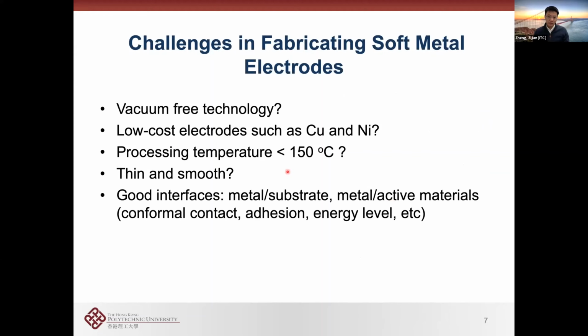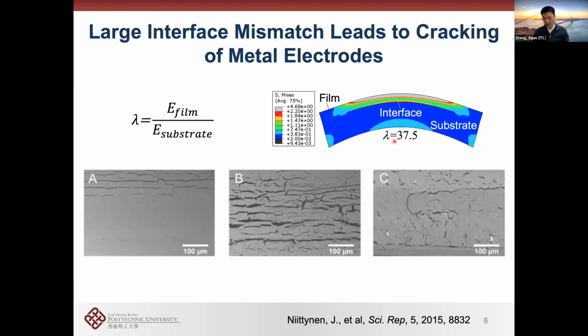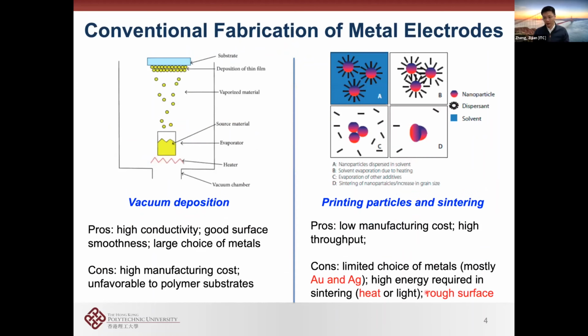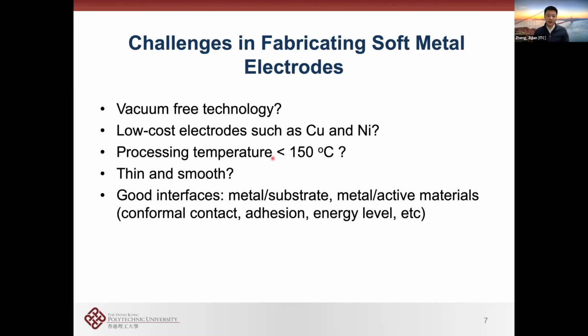So the challenge of fabricating soft metal electrodes has been one of the major issues in our field. Can it be produced with a vacuum-free technology, because polymers generally do not like vacuum environments? Can we produce low-cost electrodes such as copper and nickel, which we use all the time, rather than something very expensive? For example, printing processes typically need silver and gold, which are very expensive. Can we process at low temperature, because the polymer substrate cannot tolerate very high temperature?